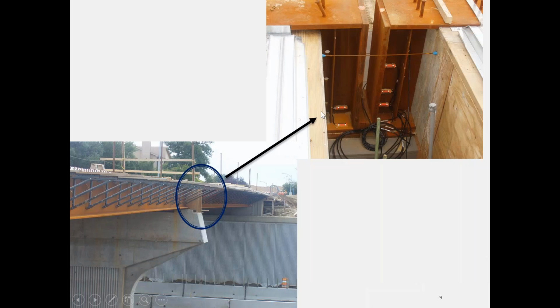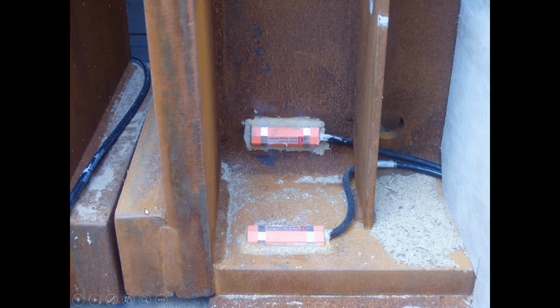So here is the detail. I hope that you can see that. Basically, over the pier, you see the portion of the girder that is embedded in the concrete diaphragm. Each end has a steel plate, end plate, and then the steel block. These steel blocks, they don't have to be full penetration weld or anything, just tack welded, because you're only transferring the compression. This is another shot on a one job. Again, in this case, you have some contact, but even if you have, let's say, a half inch or so gap between the steel blocks, you would be just fine.